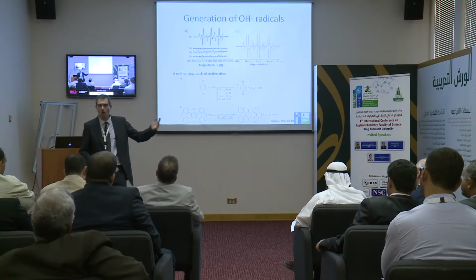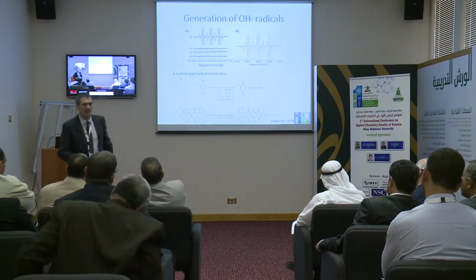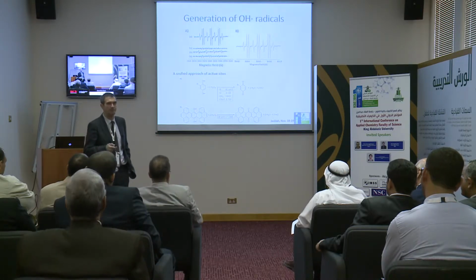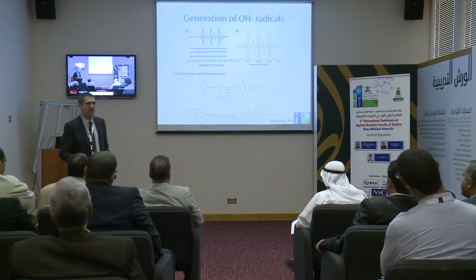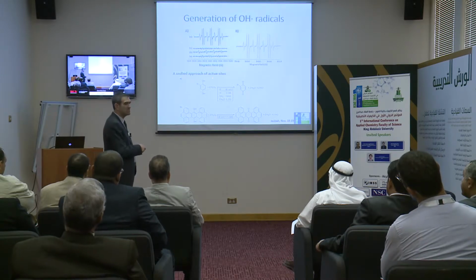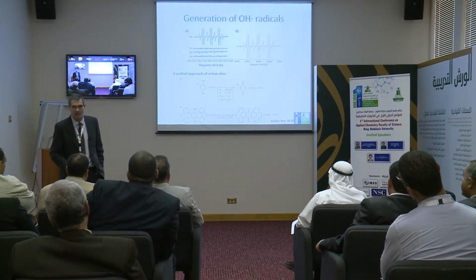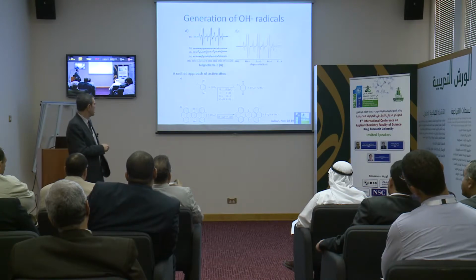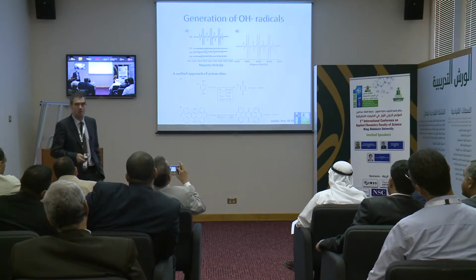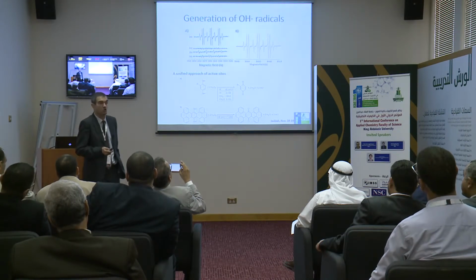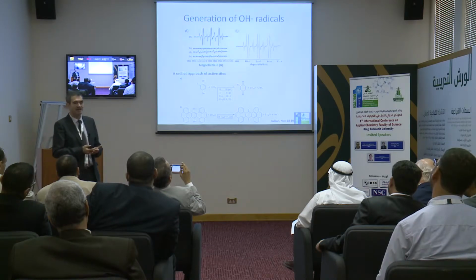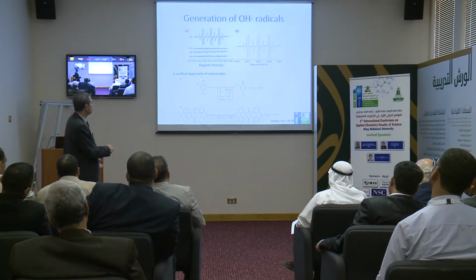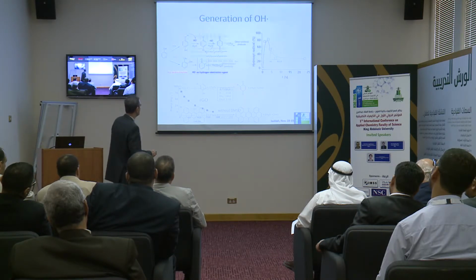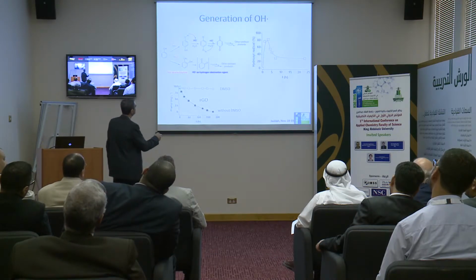Actually, in very old organic chemistry, it's known that quinone and hydroquinone is a reversible redox pair that has a redox potential very similar to iron 2 and iron 3. So the redox potential of this pair and the redox potential of iron are very similar. So there is nothing new, except that we have a graphene that should contain oxygen functionalities and many defects, and for this reason is able to promote the reaction. So this is the mechanism.